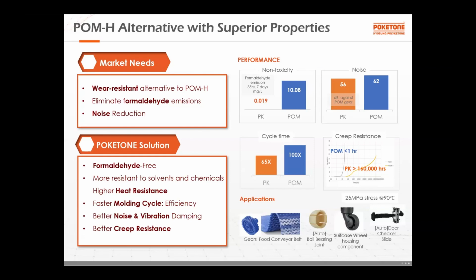If you look at the comparison of the performance, you can eliminate the concern of the formaldehyde issue, and then you can reduce the noise by about 5 or 6 decibel. And also you can reduce the cycle time about 35%. And the most important thing is that the polyketone shows better creep resistance compared to the POM material at 90 degrees C. That graph shows you the condition is 90 degrees C and 25 megapascal load.